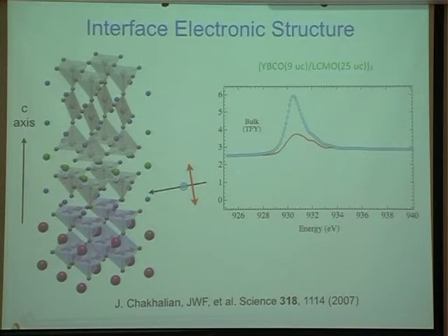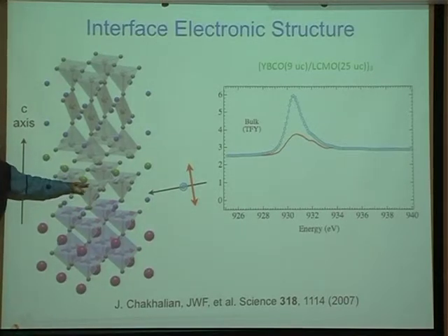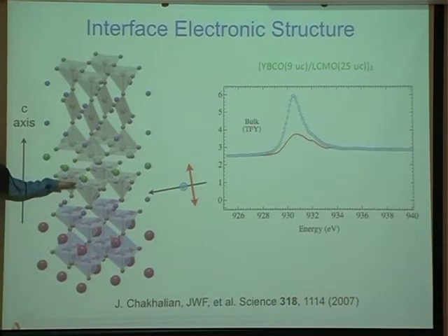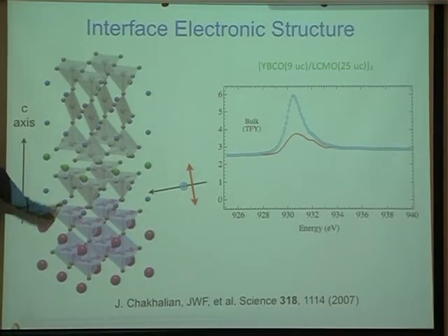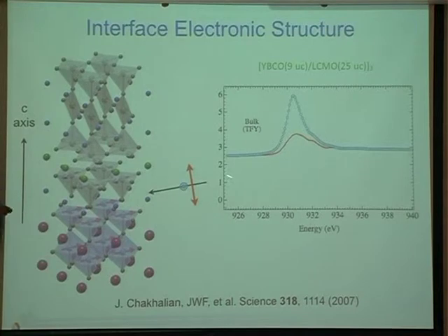This happens for a very simple reason. The cuprate has one hole in the D band, and because of this strongly broken symmetry of a very long bond here and much shorter bonds in plane, that hole sits in a planar orbital. And so the out-of-plane orbital is completely filled, so I see a very weak absorption there, and the in-plane orbital is completely empty, so I see a very strong absorption there.